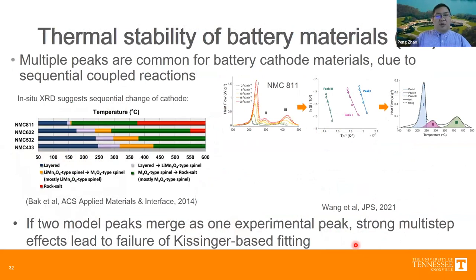And more recently, people use this to study the battery materials. As you can see, this in situ XRD will basically suggest there is a sequential transformation of the cathode materials. They start with the layered structure, it first becomes a first type spinel and then transforms to a second type spinel and eventually becomes some rock salt. So that means there can be coupling between the compositions of the material at different temperature ranges through the heating process.